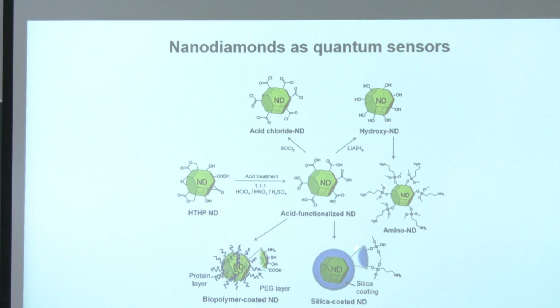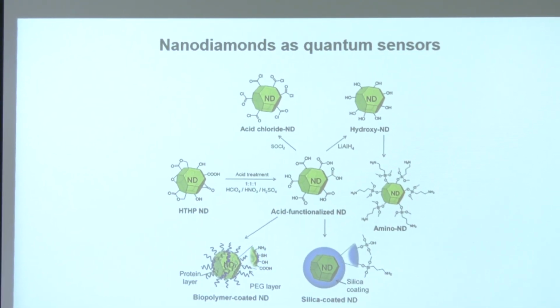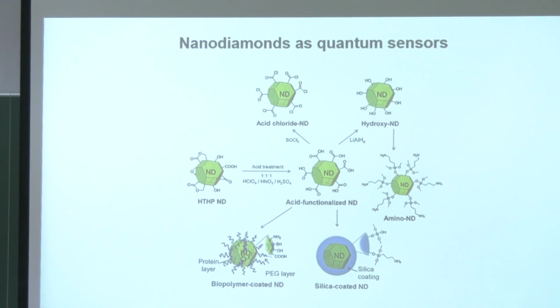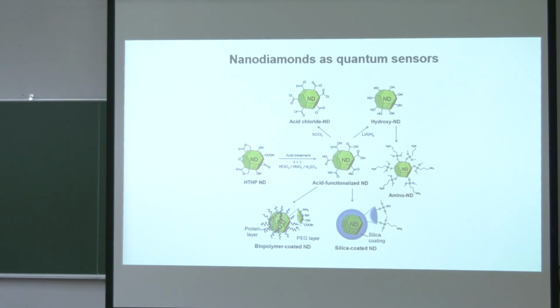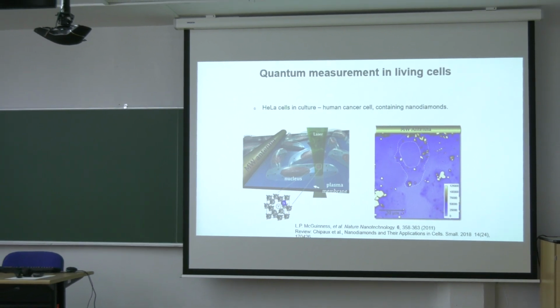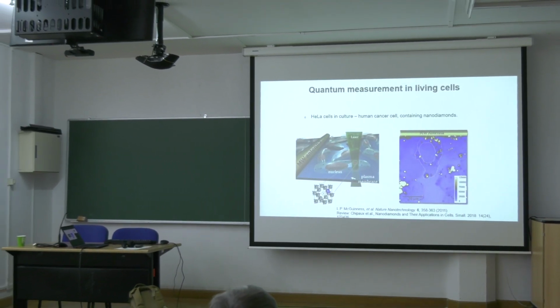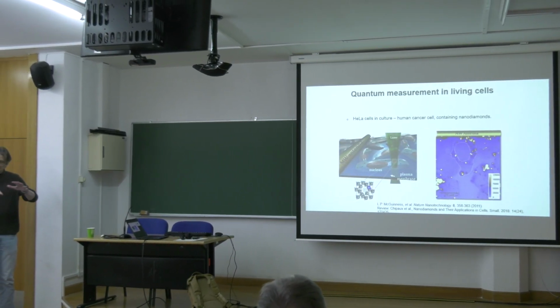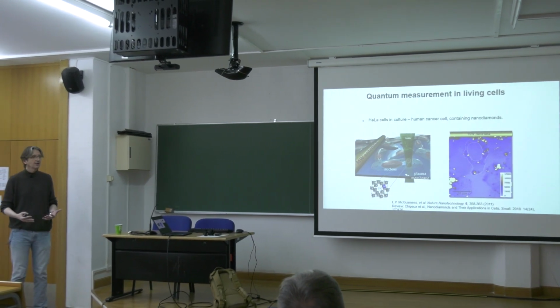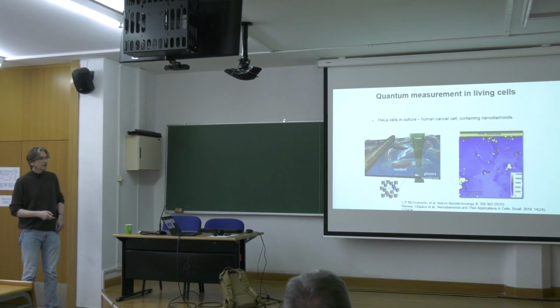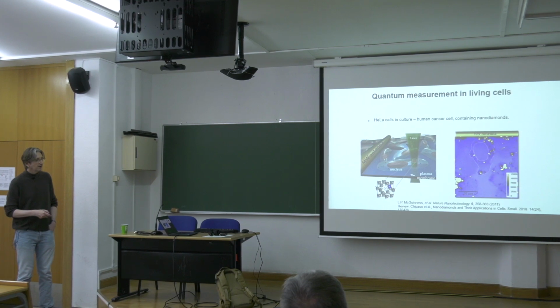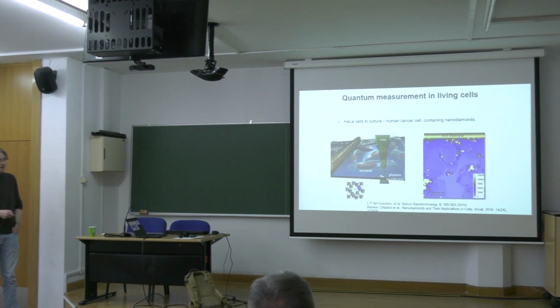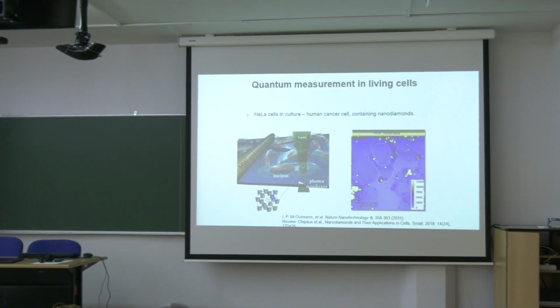There is also effort in coating nanodiamonds with silicon oxide, where the chemistry of the surface is very well developed currently by chemists. So all these types of functional groups are possible to introduce, and then by incubating living cells in a kind of solution hosting these nanodiamonds and then washing the solution out, you can look with a microscope and now find bright spots inside of cells. Those are NV centers, and so you can track them.